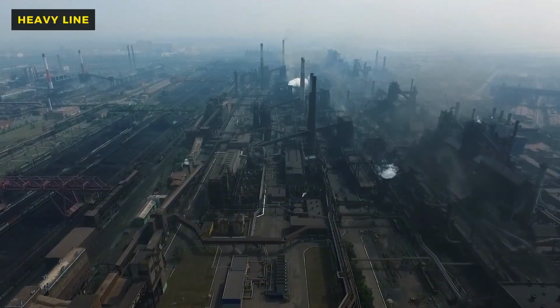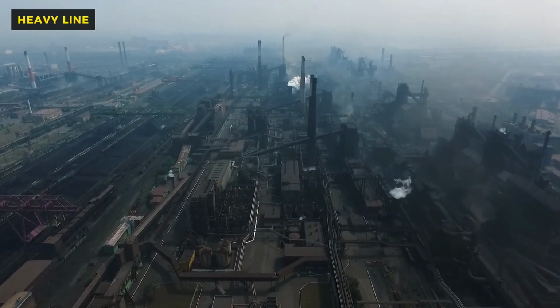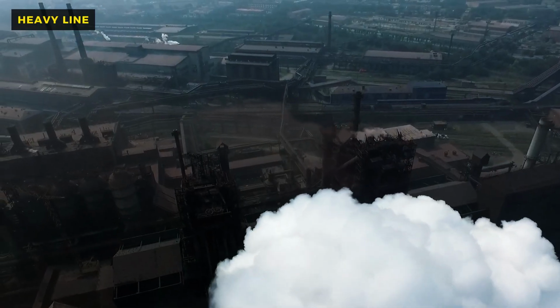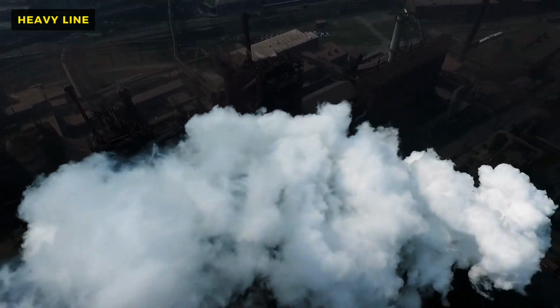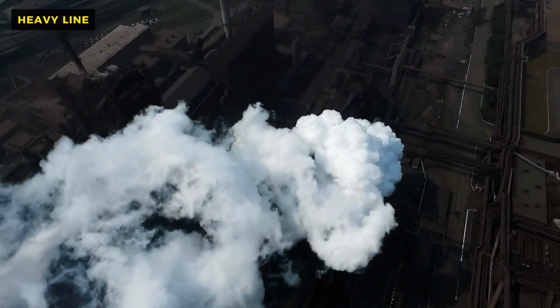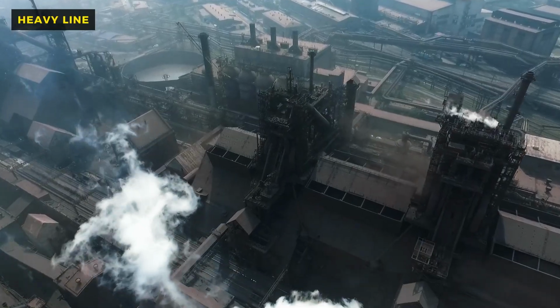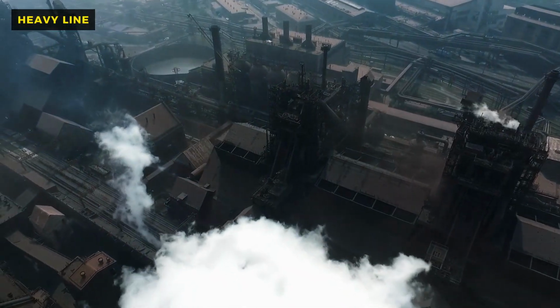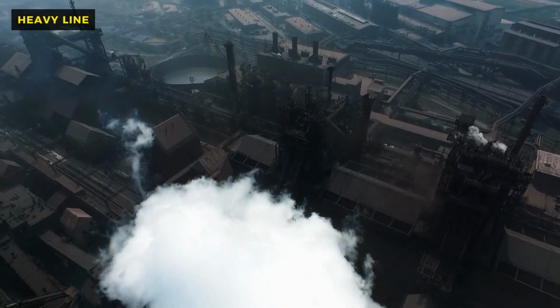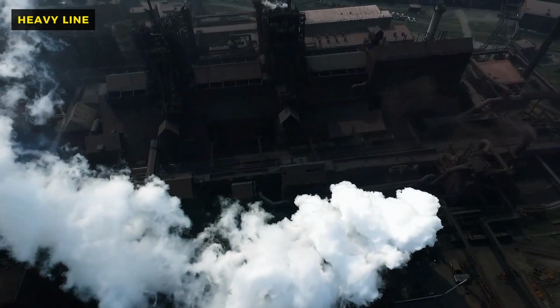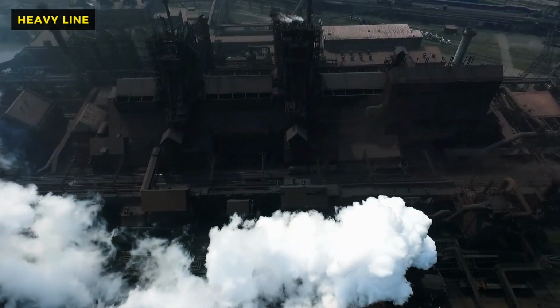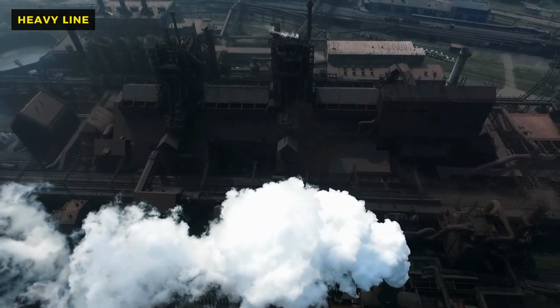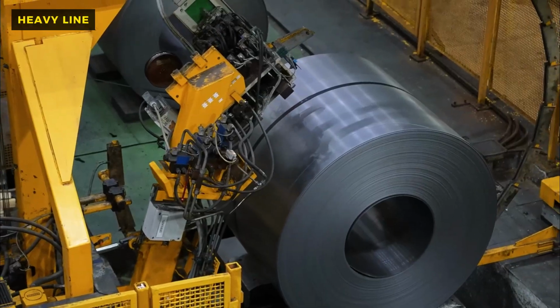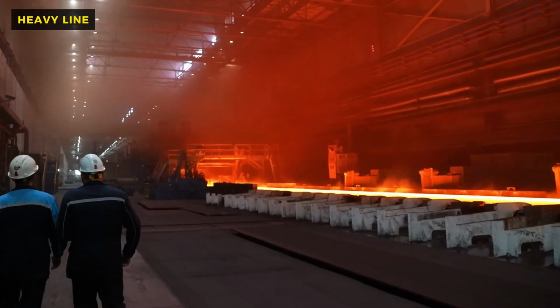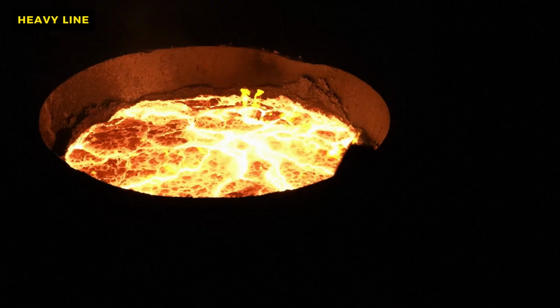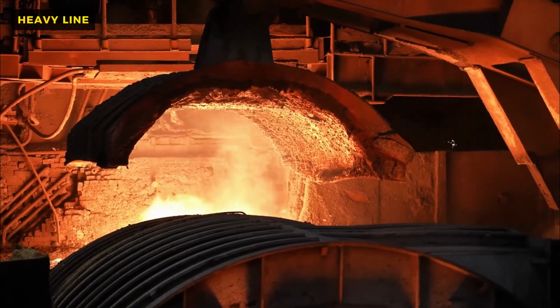At this stage, the steelmakers take samples, dipping probes into the boiling bath to check the chemistry. This is the critical moment. Too much carbon and the steel is too hard, too little and it is too soft. They add ferroalloys, vanadium for strength, chromium for corrosion resistance, tweaking the recipe with the precision of a master chef but using shovels and chutes instead of spoons. When the composition is perfect, the converter tilts and the steel is tapped into a ladle, leaving the slag behind. We now have liquid steel, 1,600 degrees Celsius, ready to be cast.